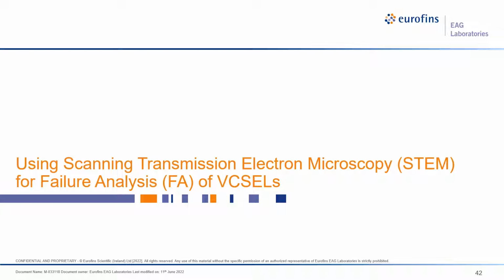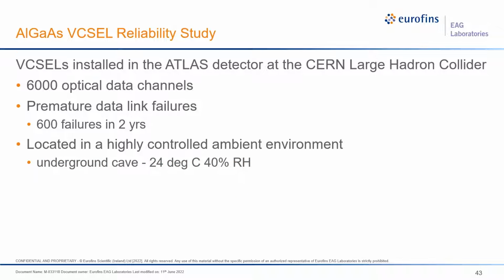But as I indicated in the very beginning of the presentation, we have many tools to bring to bear on a problem, not just SIMS. In this example, we will be showing scanning transmission electron microscopy, STEM, analyses for failure of a VCSEL. This is a unique case where EAG worked with a team of CERN scientists to capture the initial creation of dark line defects, that's DLD, networks through very sensitive reliability testing at elevated temperature and humidity.